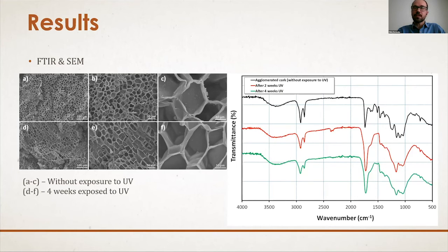And we can then try to correlate these observations with what we observed in terms of, for instance, mechanical behavior, and especially also the observations from the FTIR spectra, which clearly show some changes, even for samples exposed for 2 weeks. So we took one of the samples earlier just to check what happens with 2 weeks of exposure. But in both cases, there is a decrease in the peaks. And for instance, the ones that correspond to suberin, which explains most of the changes and degradation observed in these experiments. For instance, the mechanical behavior in terms of compressive strength and densification.